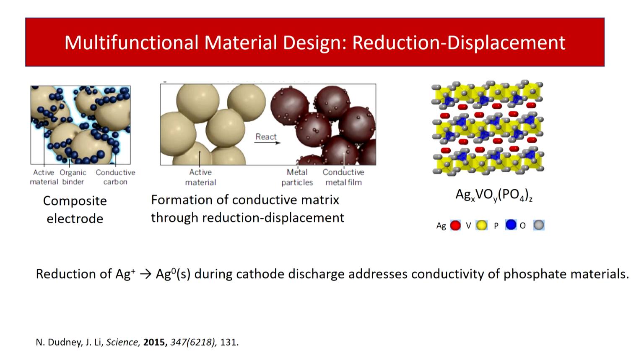So now I want to turn to the idea of multifunctional material design. Most electrodes are fabricated as something called a composite. So with the active material, we have typically a conductive additive or coating, usually carbon, then a polymeric binder, basically to take all of those powders and stick them together and have them adhere to the metal foils. So the notion that we had was if we have a material that can spontaneously form a conductive layer upon each particle through a reduction displacement reaction, this would be a way to achieve an intimate network of electrical connection within this electrode that the material could generate itself.